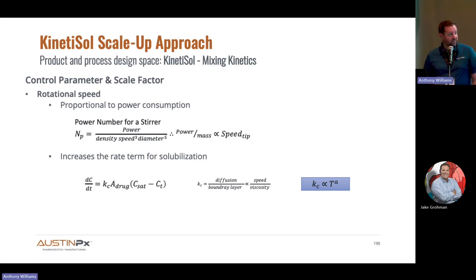I keep adding equations. I apologize, but I could have put a lot of terms here. Really, what you should see here when I talk about this dissolution coefficient is it's a relationship between diffusion and the boundary layer. And I really like the photos I saw. I'm going to talk about Dana's presentation the whole time. She showed a couple really good images where crystals were dissolving. And if you were looking closely, you could see that as the crystal was dissolving, there was another boundary where the crystal used to be. That was sort of the saturated drug layer. It was a stagnant diffusion layer that the drug has to go through to get out of the system.